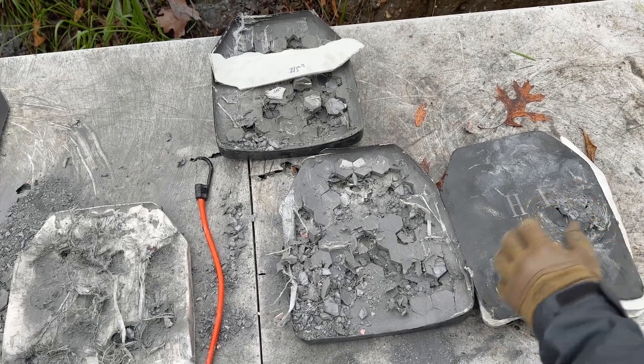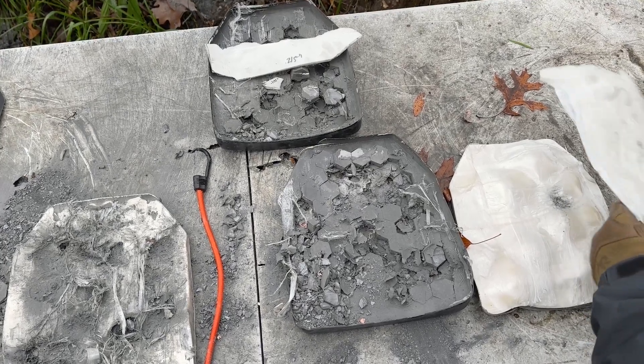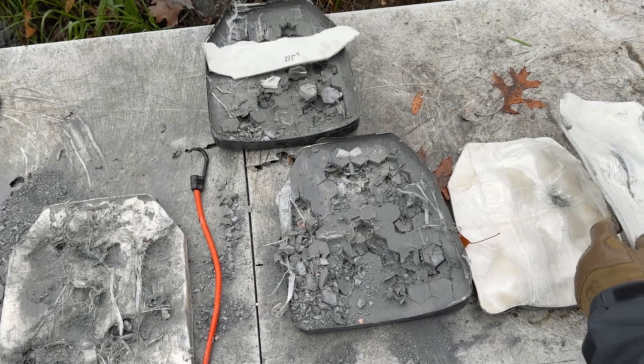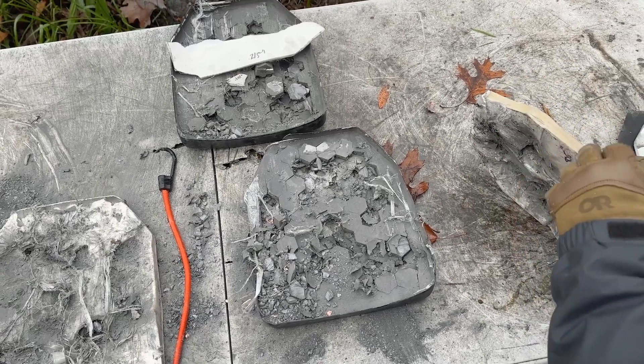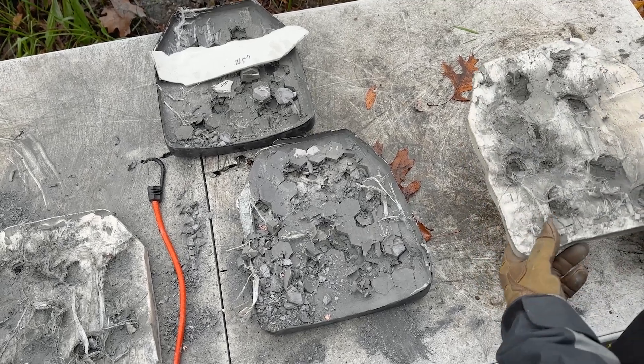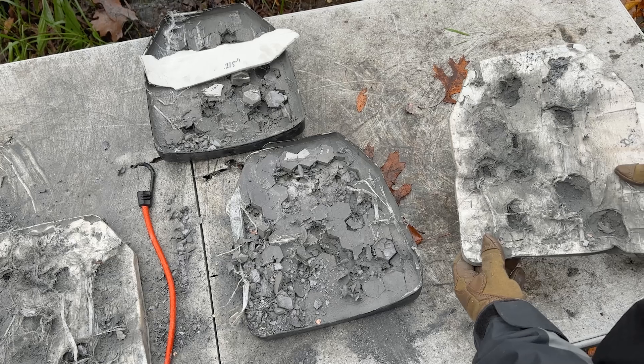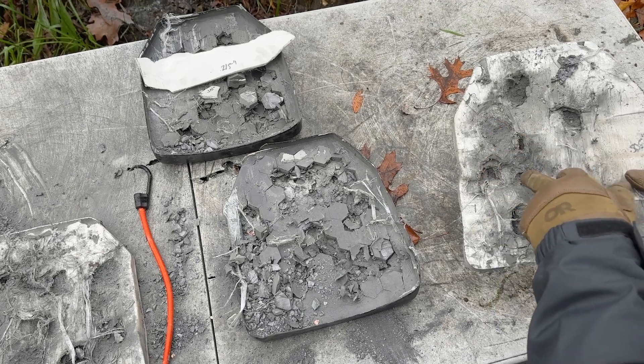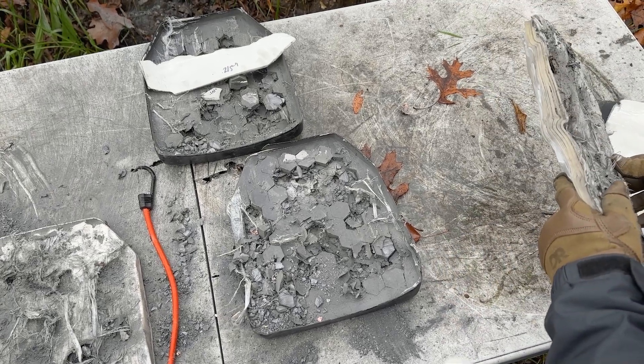Now for the fan-favorite teardown — that's where we get to see what the inside of our plates look like. Here was plate number two: confirmed our only penetration was from that M993 shot. We have a blunt force trauma foam on the back, right around 215 thousandths thick. We have our polyethylene backer — it is pressed very, very well. All that energy on this plate and a majority is still together. I measured that right around 505 thousandths. You can see a majority of hits are either stopping in the polyethylene, and the more advanced ones are getting a little deeper depending on degradation of the plate.